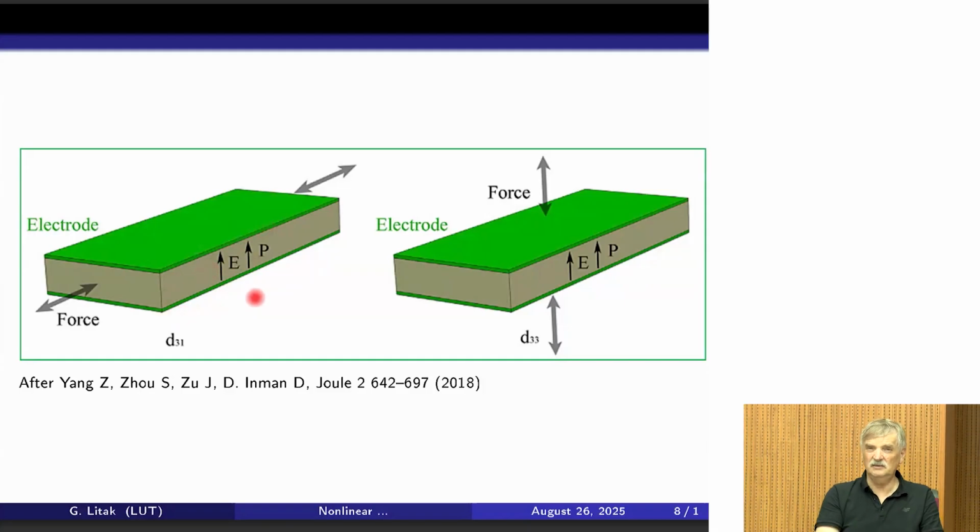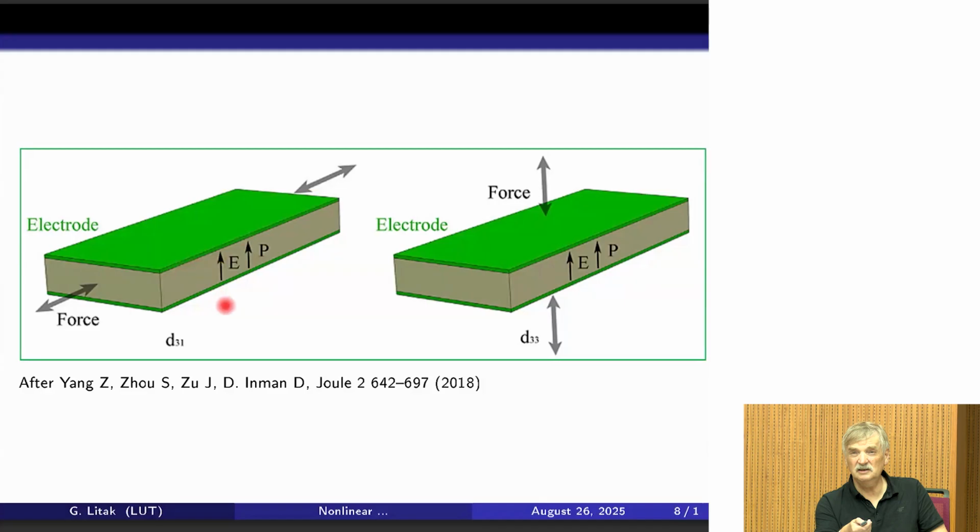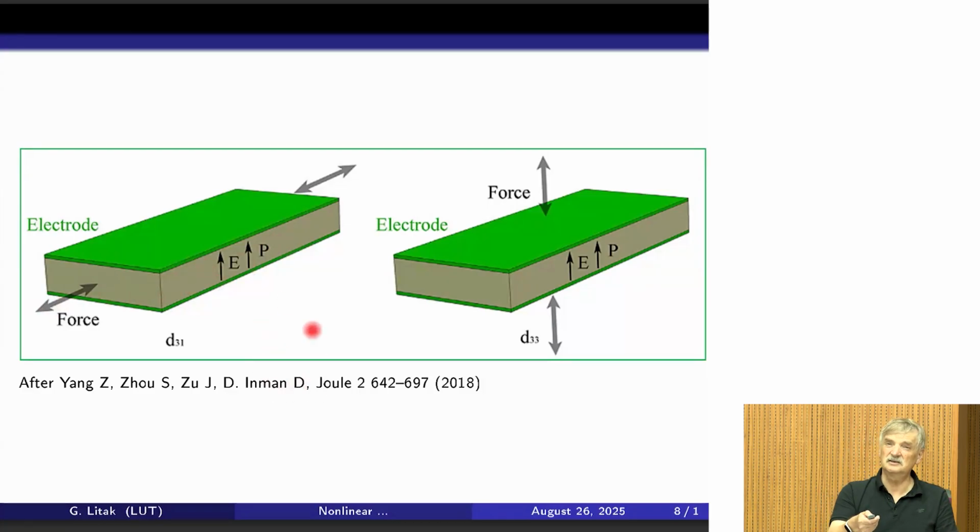So we have some play of the electrical fields from the electrodes, and also the polarization from the material. The polarization of a material is changing because we have some applied force, and when there is elongation of the material, the deformation is changing the polarization, and because the polarization is changing, we have some effect on the electrodes.